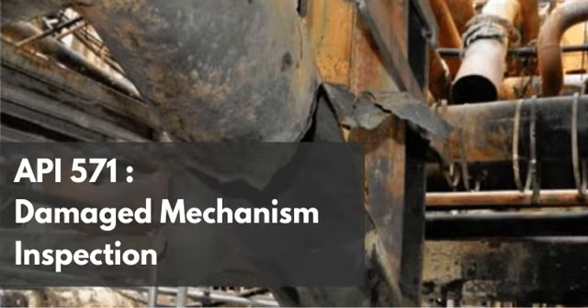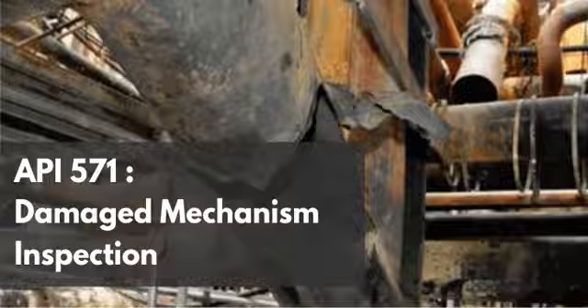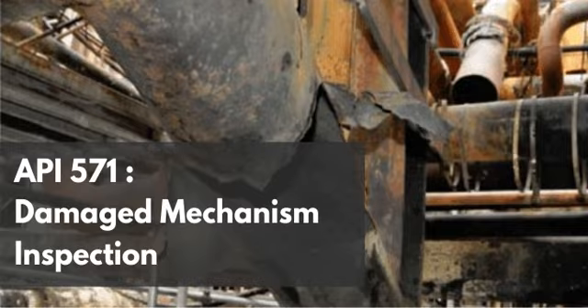Which creates a starburst pattern, or radial cracking, emanating outward from the center of the nozzle bore. Yep, a starburst. And you combine that extreme mechanical stress state with the boiling, phase-transitioning rich amine inside the reboiler. You have the perfect storm for rapid, localized failure. It's a textbook example of how mechanical design features dictate the exact location of metallurgical degradation.